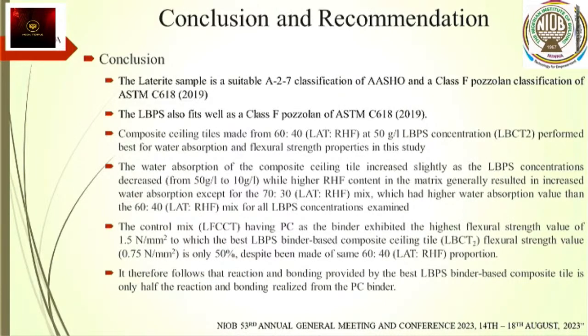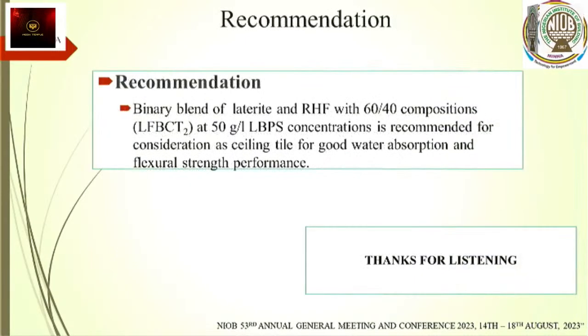We believe we have not gotten there, but it's an indication that working on 60-40 laterite to RHF, we should be able to arrive at a good tile from this material. So in recommendation, we said binary blend of laterite and RHF with 60-40 composition at 50 grams per liter.